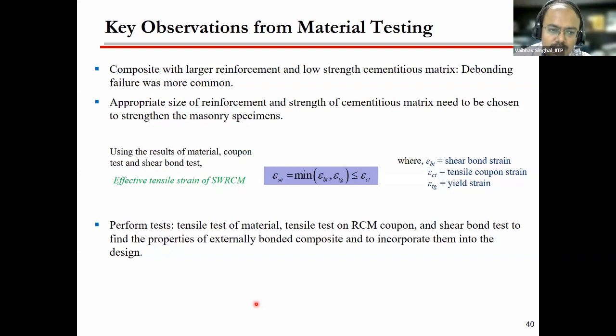this method. And by performing the various tests, the test on the reinforcing material, the tensile test on the coupon of the reinforced cementitious matrix, and the shear bond test, you can find out the effective strain, and ultimately you can find out the effective stress. You can think of it like a design when you do a design of reinforced concrete, any material, where we see the yield strength of a material, and we see how much is the bond strength, whether there is sufficient bond strength available or not. Accordingly, we provide the development length. So all these design concepts will also be applicable for this reinforced cementitious matrix. So you need to find out the bond strength, the tensile strength, the material strength to get the effective stresses which can be taken by this strengthening material.